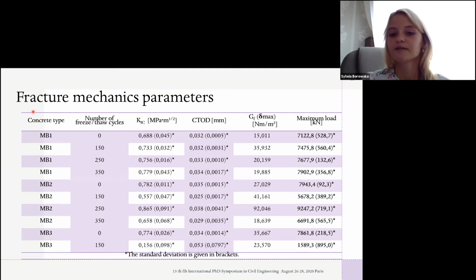The results show the improvement of fracture energy and fracture resistance of high-strength concrete by adding steel fibers and the mixed fibers. But after 150 freeze-thaw cycles, there was a decrease in the stress intensity factor values of concrete with steel and basalt fibers. Concrete with a mixture of steel and basalt fibers has lost its resistance to fracture after 150 cycles of freeze-thaw. The value of the critical tip opening displacement in this case is highest.